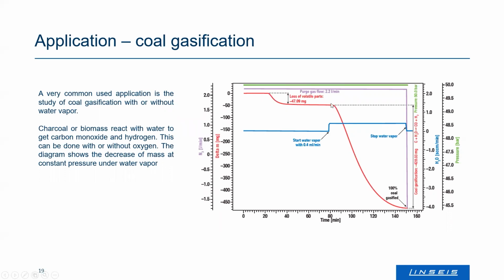And after a certain time at target temperature, you start to add in water vapor. This blue curve shows the water vapor flow. So it was activated over here. Once you start adding in the water vapor, the sample mass suddenly starts to decrease rapidly, because the coal reacts with the water vapor according to the equation. Carbon plus water gets carbon monoxide plus hydrogen, and any further it forms methane gas plus water again, and so